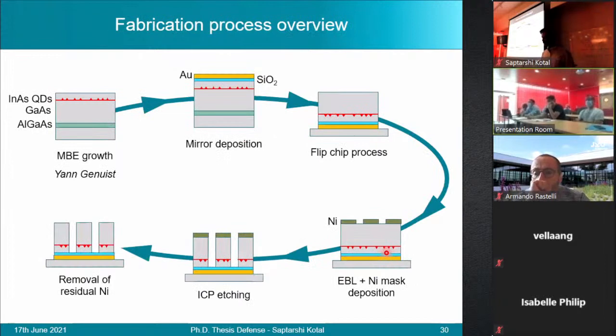To fabricate these devices, we begin by growing with molecular beam epitaxy, which was carried out by Yann Genuist. We have the growth substrate, followed by a sacrificial aluminum gallium arsenide layer. Then the gallium arsenide that will form the nanocavity, which sandwiches a sheet of indium arsenide self-assembled quantum dots. The next step consists of depositing the hybrid silica gold mirror. Then, with a flip chip process, we glue the mirror side onto a new host substrate and get rid of the growth substrate and the sacrificial layer.